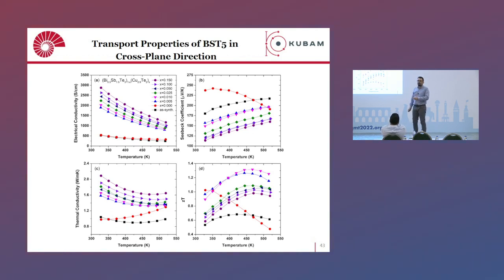So the main thing is this: bismuth antimony telluride has a very small band gap. If we do ball milling on this material, probably we are also changing the composition and the electronic structure, which means probably we are shrinking the band gap. And if we shrink the band gap, as you know, if you increase the temperature, at one point the minority carriers, let's say this is a p-type material, the electrons will jump from the valence band to the conduction band, which will basically kill the Seebeck coefficient. So what is going on here is purely a minority carrier effect. We are activating the electrons as opposed to holes because of the shrinkage of the band gap due to purely